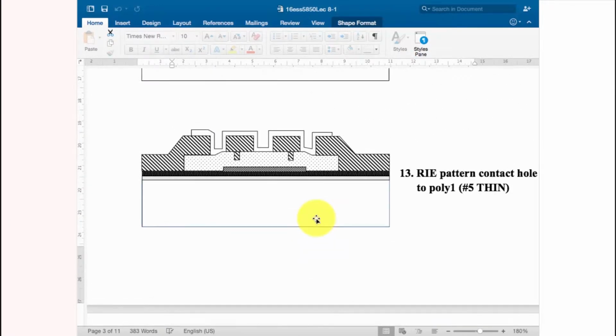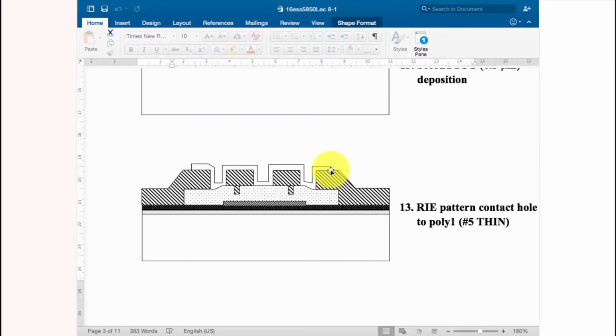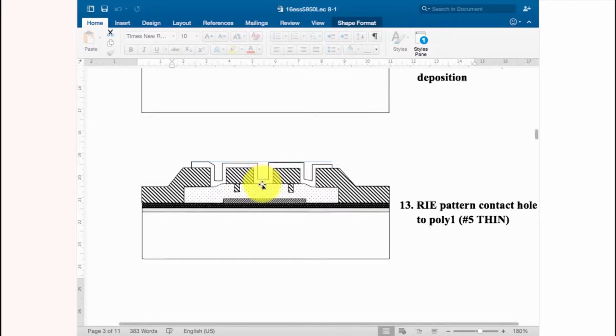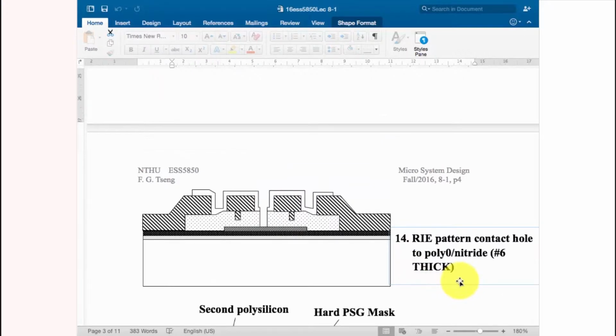Actually, we need to notice in the second sacrificial layer patterning, we have two different commands. One command is related to where we only pattern the thin second sacrificial layer. So this process we call the thin layer etching. We don't etch the thick layer. However, in some other cases, we want to contact the second poly to the bottom structure. In this case, if you only puncture holes in the second sacrificial layer, this is not deep enough. So we need a second command we call the thick layer etching process. The thick layer etching process can punch through not only the second sacrificial layer, but also the first sacrificial layer together. So you are able to contact from the second layer down to the bottom surface.